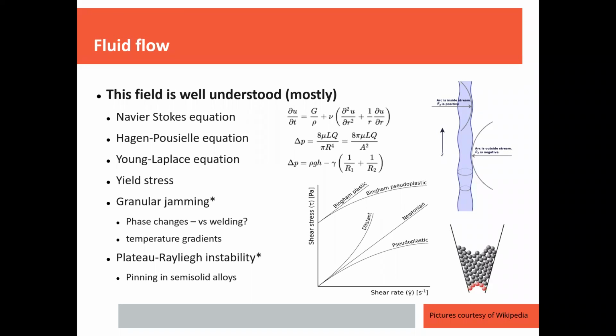And if anyone's familiar with the wire production industry, you usually use a wire rolling mill, and you roll it through maybe tens, maybe hundreds of times to get really small diameters. So small diameter wire needs a lot of processing to get it to that diameter. With this sort of process, you could continuously cast very small diameter wires, which is very interesting, separately even from the semi-solid metal 3D printing. So that I think is worth looking into if anyone's interested.